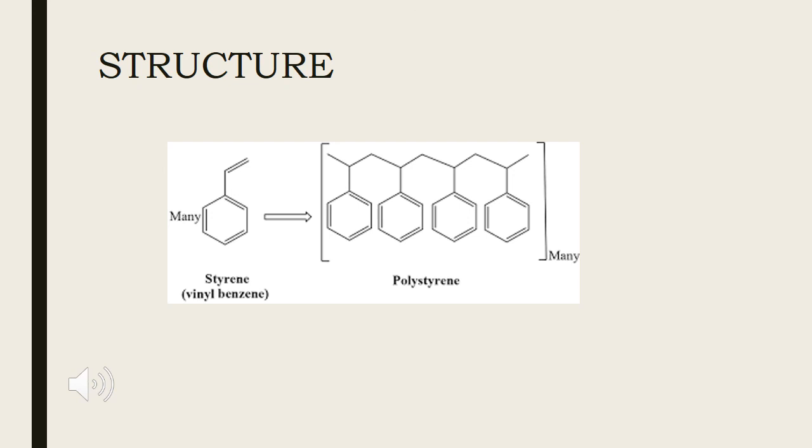The intermolecular weakness versus the high intramolecular strength due to hydrocarbon backbone confers flexibility and elasticity. The ability of the system to be readily deformed above its glass transition temperature allows polystyrene and thermoplastic polymers in general to be readily softened and molded upon heating.